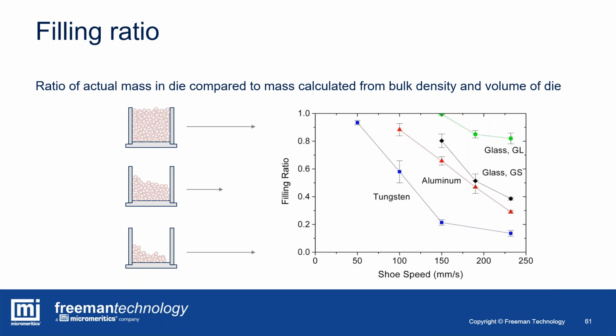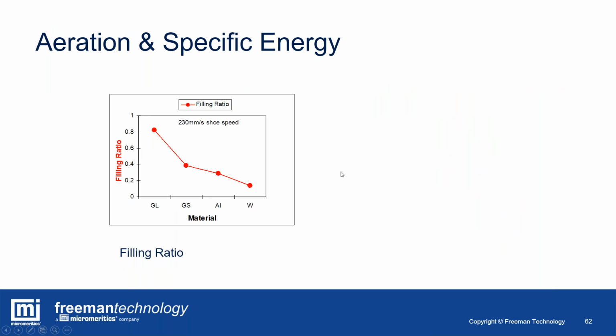So what we can do is we can use this process performance, let's say this fill ratio at 230 millimeters per second, to quantify how these material properties influence behavior within the shoe and die filling system. So if we have a look at that filling ratio plotted for the 4 different materials, we've got 82% for the large glass beads, and this is again at that highest shoe speed, 230 millimeters per second, down to about 15% for the tungsten. So let's have a look at some of the material properties.